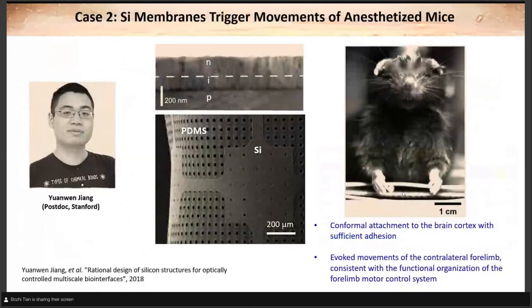While the coaxial silicon nanowire can only target a single cell, if we hope to target tissues or organs, we probably need to use a different material. And one option is this multilayer silicon membrane, which can also contain P-type, intrinsic, and N-type domains. This work was done by my former graduate student, Yuanwen Jiang, and he is currently a postdoc at Stanford. In this work, he synthesized this multilayer silicon membrane using a chemical vapor deposition process, and then used a lithography method to make a material we call silicon mesh structure.